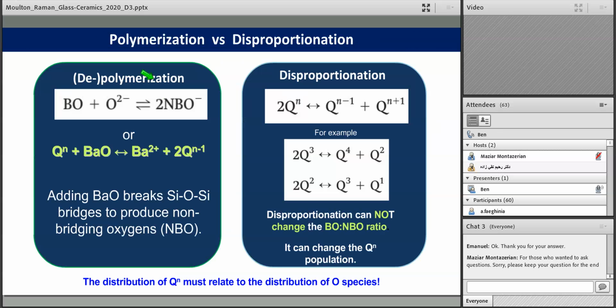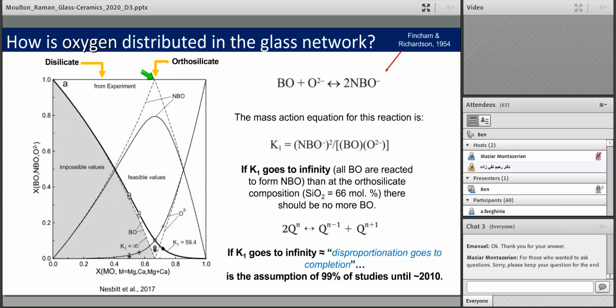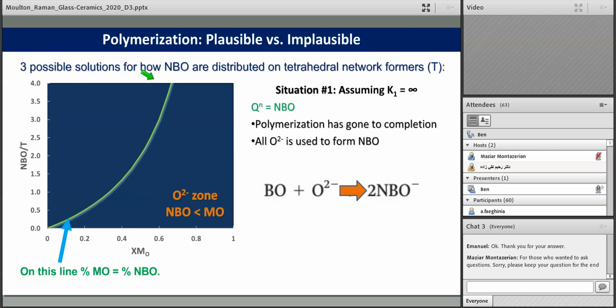So if we go to the mean connectivity we introduced in a moment and look at how these non-bridging oxygen are distributed across the tetrahedron, there are 3 situations set up. Situation 1, under the assumption that K1 goes to infinity, results in the NBO over T. Remember, there can be 4 oxygen per tetrahedron, so 0 non-bridging oxygen to 4 non-bridging oxygen. And here it increases non-linearly to the orthosilicate composition, 66%, where all the oxygen on the tetrahedron is non-bridging oxygen.